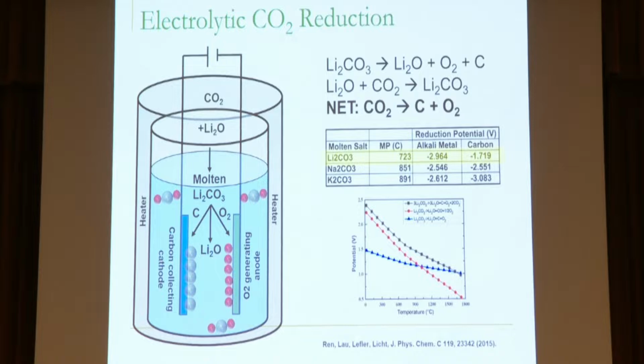And the key thing here is to make sure we look at our reduction potential. This is a key theme, making sure the chemistry and physics works, right? For something like lithium carbonate, the reduction potential of the carbon is going to happen first before the alkali metal, right? So this ensures that we're actually reducing the carbon. We're not reducing the lithium or whatever other alkali metal system we have in there.